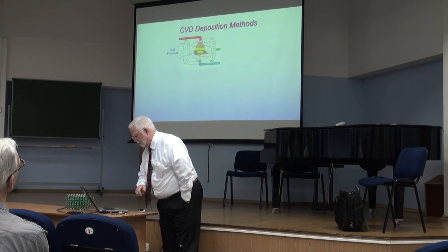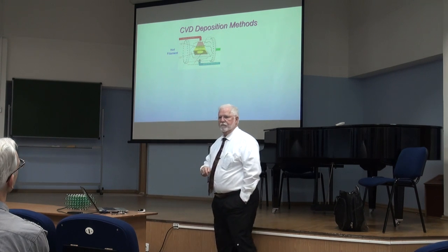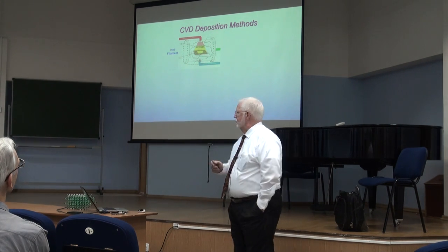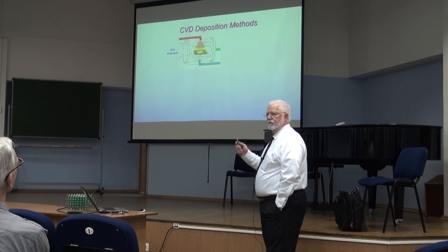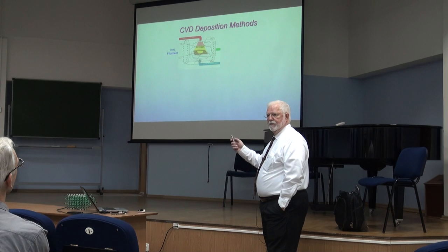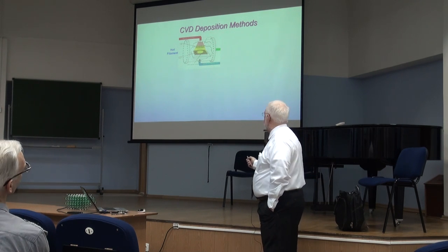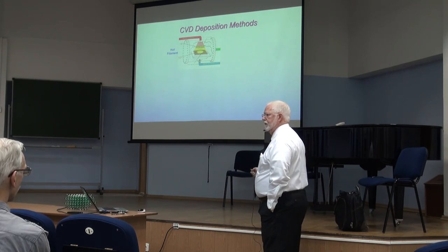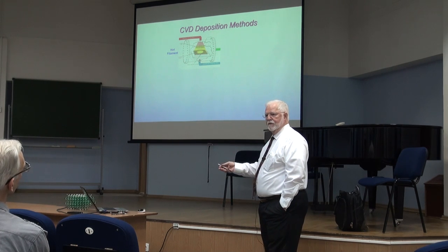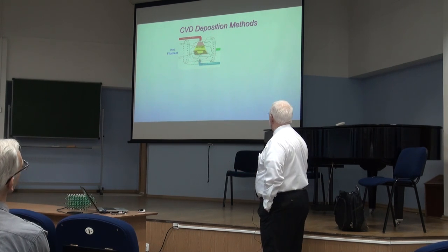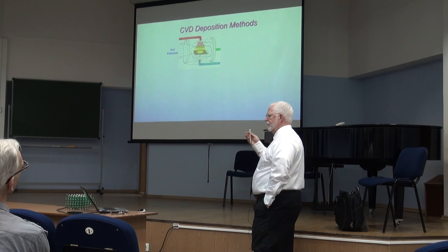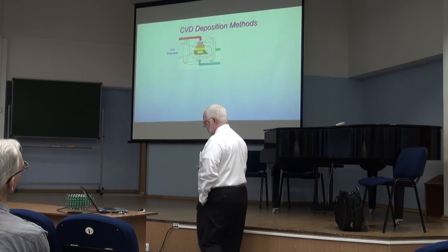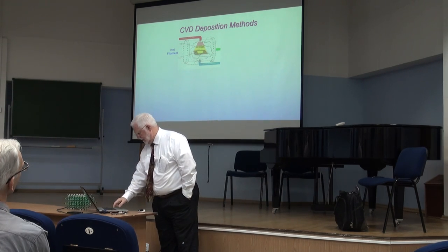We've shown many different ways to grow diamond. Actually, one of the first, before the plasma technique, was the use of a hot tungsten filament, the same color temperature as a light bulb. So this is typically 2400 degrees C. And again, the role of that filament is simply to dissociate molecular hydrogen into atomic hydrogen. You introduce a little methane, chemistry occurs in the gas phase, it gets to the surface, and you now have a flux of atomic hydrogen and hydrocarbon radicals that can grow diamond.